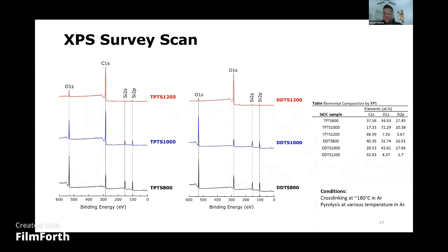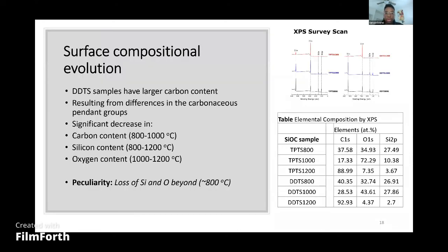In order to find the surface composition of these materials, we utilized XPS surface scans, as shown in this slide. From the results, it's apparent that samples derived from DDTS consistently have a higher carbon content independent of their pyrolysis temperature. This is likely due to the fact that in DDTS polymeric precursors, we do see the addition of phenyl pendant groups, which are high molecular weight carbonaceous pendant groups, instead of vinyl pendant groups, which are present in TPTS-derived ceramics. Similarly, in all of these materials, we do see a significant decrease in the amount of carbon between 800 and 1000 degrees centigrade, in the amount of silicon between 800 and 1200 degrees centigrade, and in the amount of oxygen between 1000 and 1200 degrees centigrade.